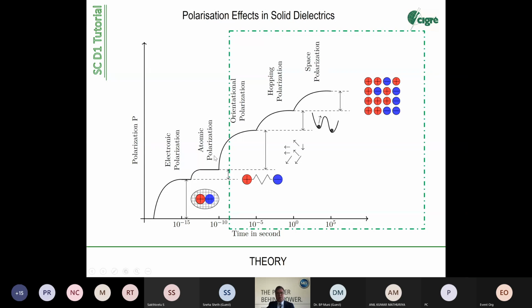That's the range we are looking into the physics when we talk about composite insulating materials. Electronic and atomic are too fast. They are not interesting for us. They are more interesting for electronic materials. For example, in this range, space charge and ionic polarization, we mainly talk about the Maxwell-Wagner effect. Maxwell-Wagner effect is a dominating effect in composite insulating materials since it acts at interfaces. So you charge or discharge space charges or ionic particles in and along interfaces. So the Maxwell-Wagner and so-called accumulator effects, these are the main effects we have to look into.